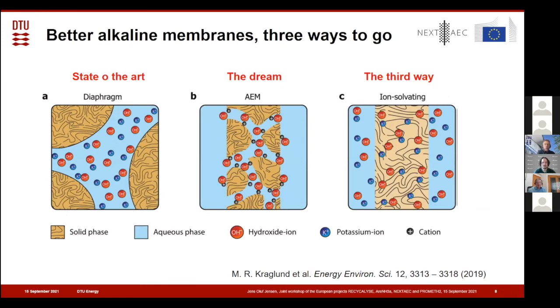The diaphragm is the porous membrane used today. It's quite thick to have a reasonable separation of the gases and to have a high bubble point. And that gives a quite high resistance because of the thickness. So the state of the art material, the Zirfon, is 0.5 millimeter thick. The dream is to make an anion exchange membrane like the one in PEM electrolyzers, where you have a system with side chains with immobilized ions, and then you can make wetted hydrophilic domains that conduct the ions. You can see that as a kind of nanoporosity filled with water and ions.